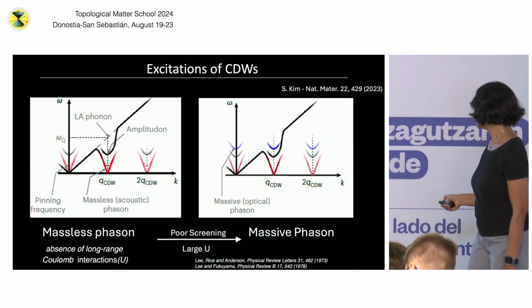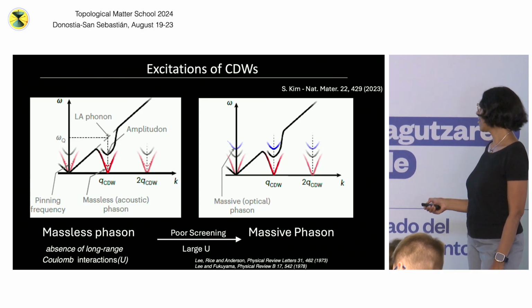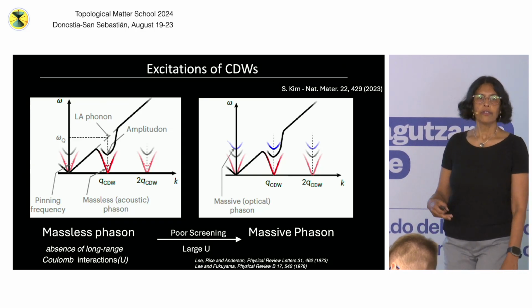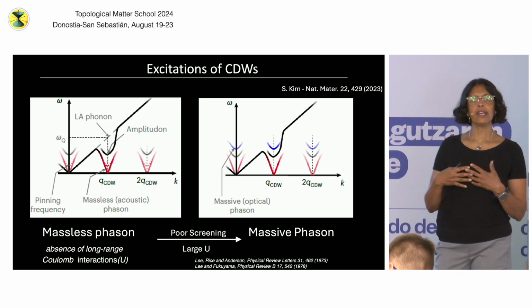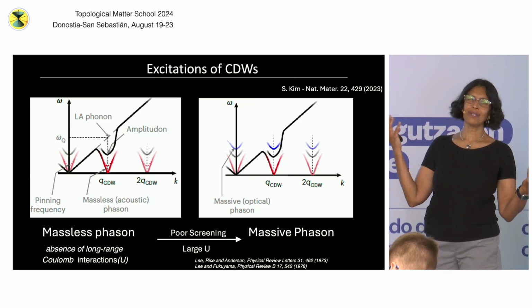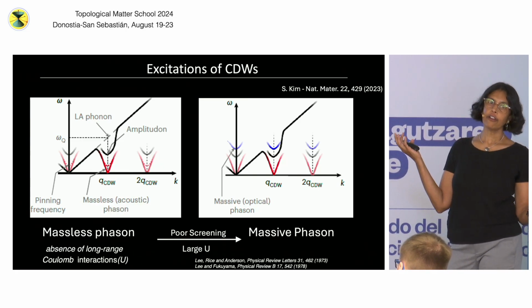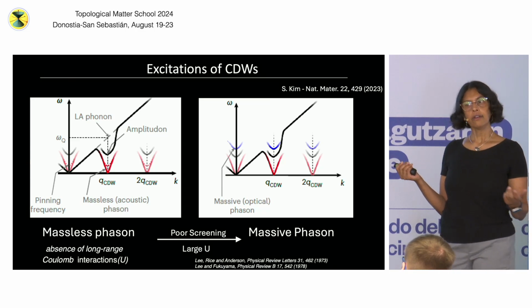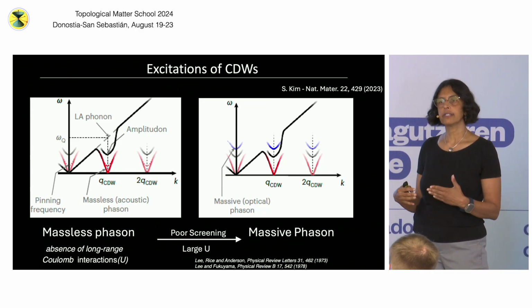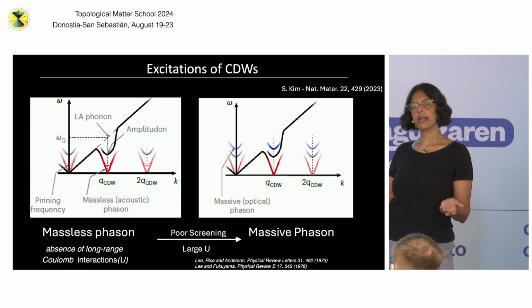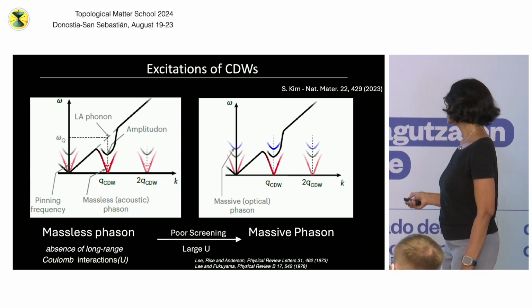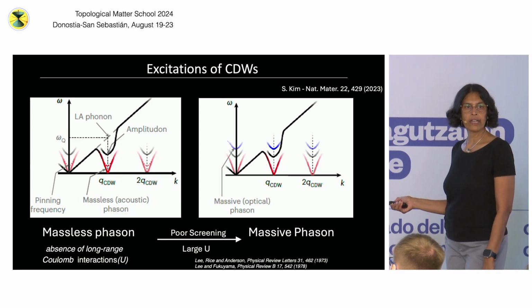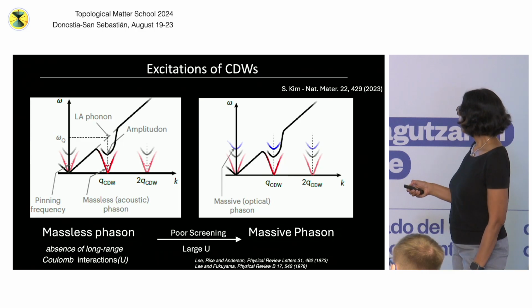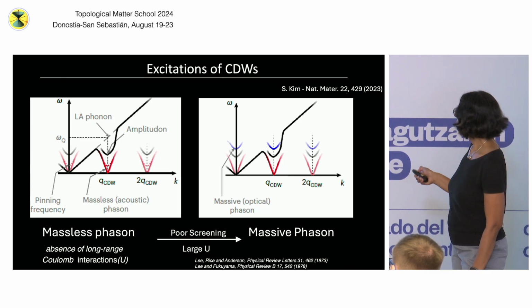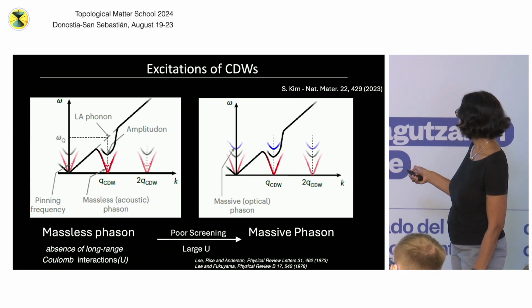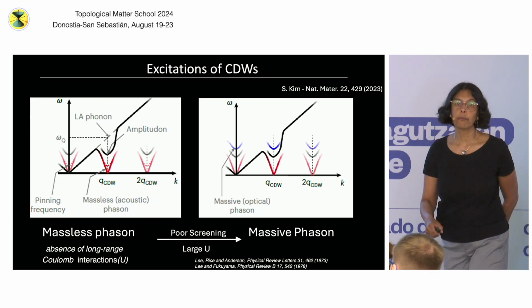Now, in 1973 and 78, Lee, Fukuyama, Lee, Rice, Anderson, they wrote a couple of papers, in fact, there were more than 2, that showed that when you have poorly screened Coulomb interactions in a system, so remember, CDWs usually occur in metals where screening is really good. However, if you have a CDW in an insulator, right, the CDW actually gaps out your entire Fermi surface, then you can have very poor screening. Or for some reason, if your density of states is very low, you can have poor screening and therefore large long-range Coulomb interactions. And if this happens, then your massless acoustic phase mode can acquire an even larger mass, so it can go from here to here. So your phason can acquire a pretty large mass.